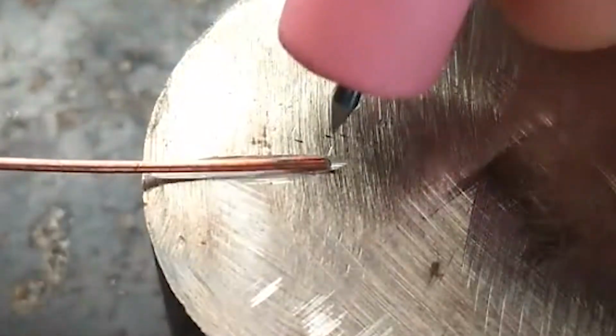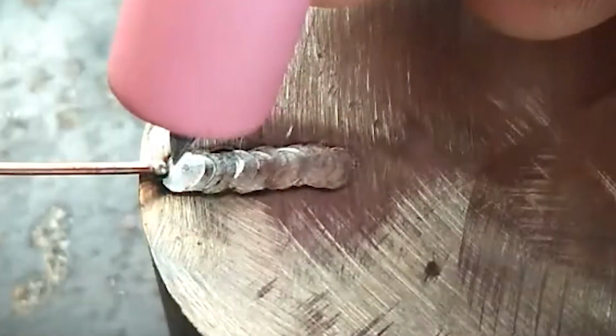It is currently the most widely used welding method in some processing industries such as kitchenware, doors and windows, stainless steel work pieces, etc. Advantages are high current density, heat concentration, high deposition rate, and fast welding speed. In addition, it is easy to start the arc. The disadvantages are large thermal damage to the welding material, large deformation of the work piece, and the solder joints are prone to blackening. The solder joints are brittle after high temperature annealing, and they are prone to cracks and lead to leakage. Since the arc is strong and the smoke is large, it is necessary to strengthen the protection.